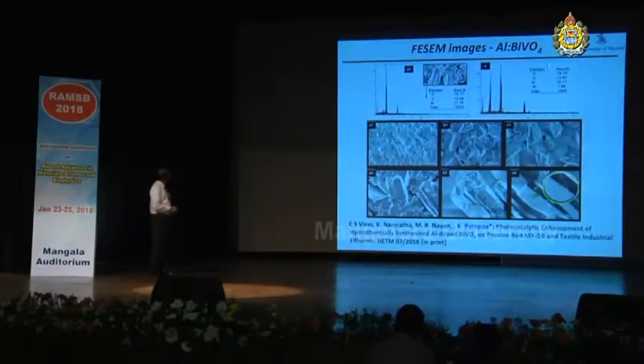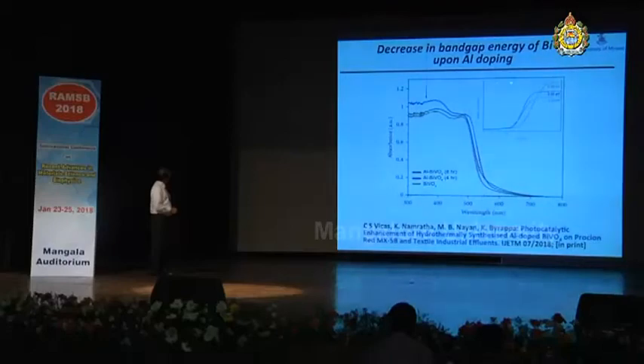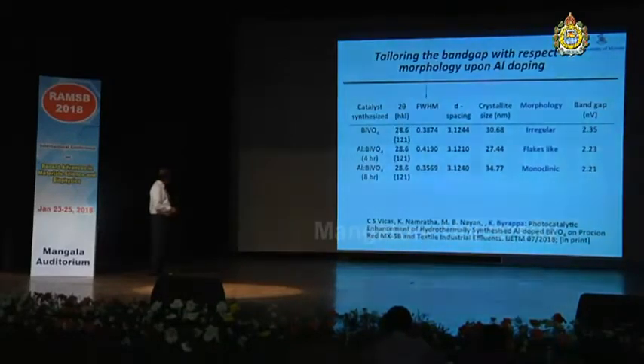And now we have also doped this bismuth vanadate with aluminum in order to enhance the photocatalytic activity of the Procion Red MX-5B, and also some textile industrial effluents collected from Reed and Taylor industries near Mysore. And similarly, this shows the decrease in the band gap energy with aluminum doping, and these are the different concentrations. Aluminum doped bismuth vanadate obtained with different experimental duration, and the band gap is varying here, and the size of these crystallites as calculated from the powder X-ray diffraction patterns, and the morphology varying from irregular shapes to flakes and monoclinic crystallites.